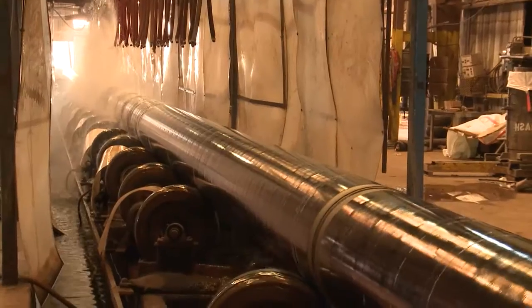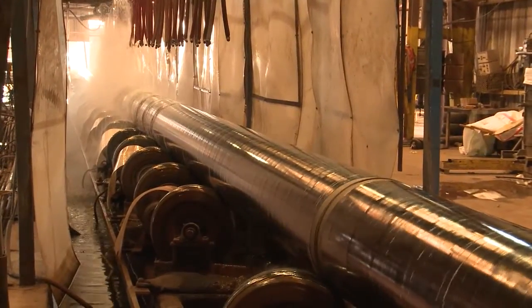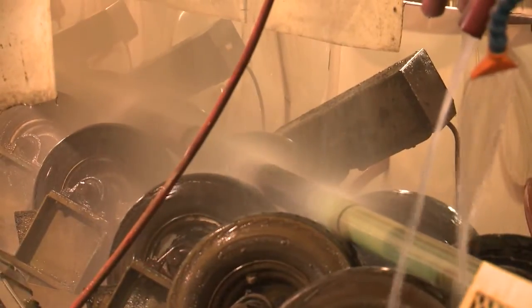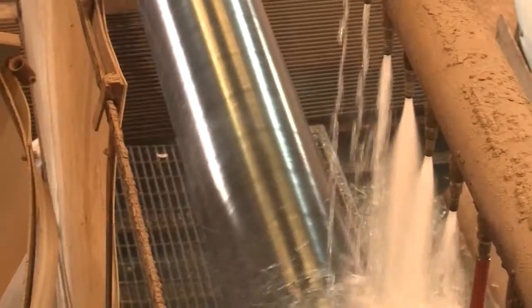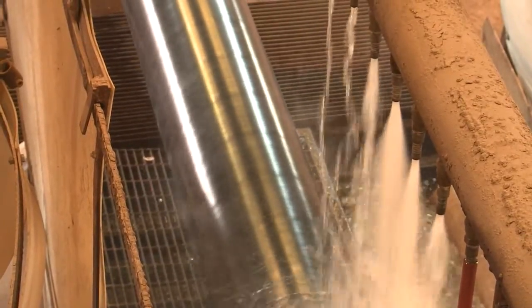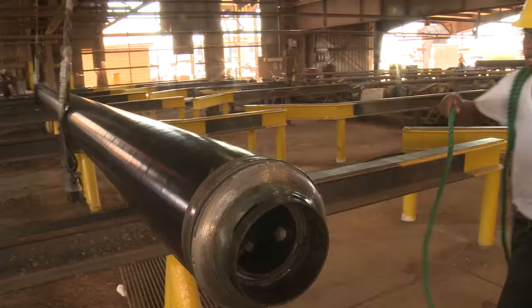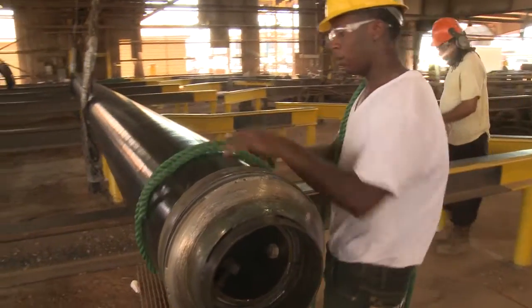The cure time is the time it takes for the FBE powder to finish its reaction and fully harden. If the coating doesn't achieve full cure, the coating will not perform adequately. Plus, the ring sample testing will fail, creating rejects. Then the pipe goes to the outbound rack.